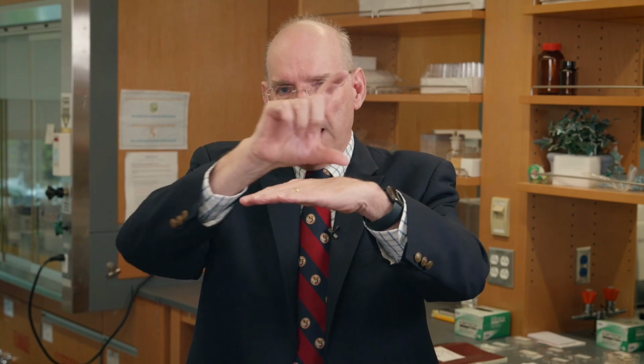And sputtering works in this way. You start with a block of solid chrome. You put a gas in here, and you turn it into a plasma. You basically strip off the electrons, makes the gas atoms charged, and then you can use the charged atoms, accelerate them into the chrome target, and that knocks the chrome atoms out, and they drift back through the plasma and land on the substrate where you're trying to grow this film. This is a complicated process. It has lots of different parameters that you can control, but you can make a chrome coating, and you can control the properties of that chrome coating over quite a range.